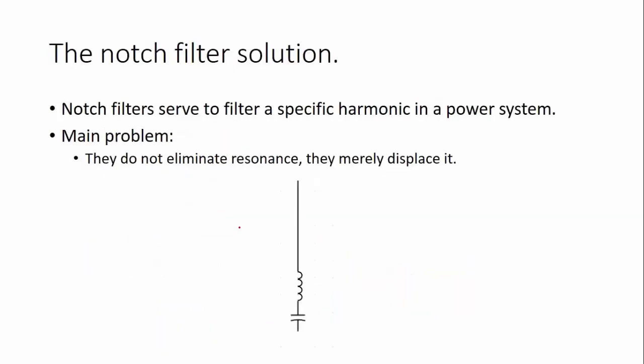Now, normally, when we have harmonic content in a system, the most popular and the cheapest solution is the notch filter. When you want to filter a harmonic from a system, you may install a passive filter, which is the most popular and the cheapest way to free harmonic content from a system. That filter will drain the tuned harmonic to the ground. Let's say this is a fifth harmonic filter, which is very popular. All the fifth harmonic current will flow through here to the ground and will not dwell in the system. It will not cause distortion in the system impedance.